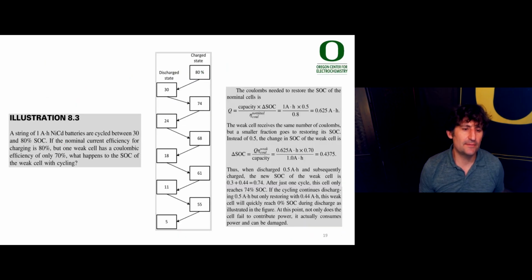So let's look at an example. This is illustration 8.3 from your book. Imagine you're cycling a battery. This is a nickel cadmium battery. You're cycled between 30 and 80% state of charge. Now, if the nominal current efficiency for charging is 80%, that means that's what the manufacturer has provided and what's the spec. But there's a weak cell that has a coulombic efficiency of only 70%. What happens to the state of charge of the weak cell with cycling? Well, you might start at 80%.